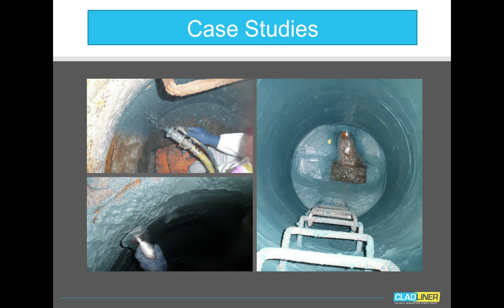As you can see by the finish, it gives you a nice, lustrous, shiny, colorful finish that ultimately will prevent the hydrogen sulfide from breaking down the concrete, as well as prevent any I&I from infiltrating into the structure later. At an application of a 1/4 inch thickness or more, I&I can be controlled with the epoxy modified mortar. Hydrogen sulfide, as we saw by the test, should be no concern when it comes to application of Cladliner in that kind of environment.